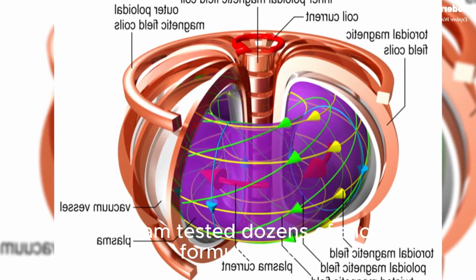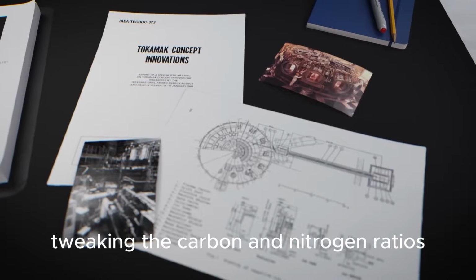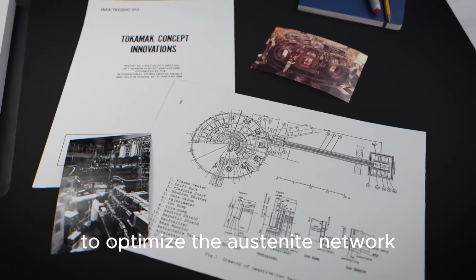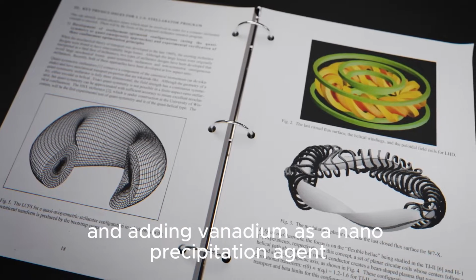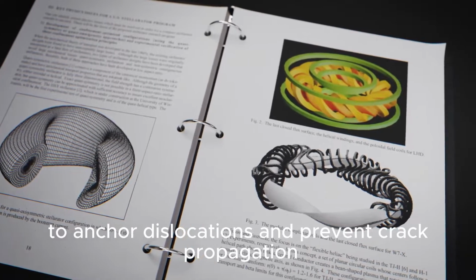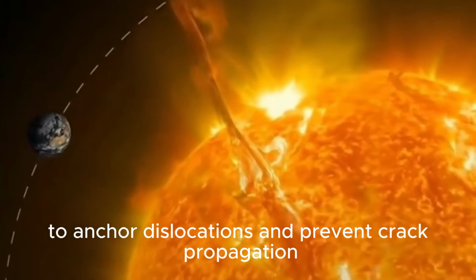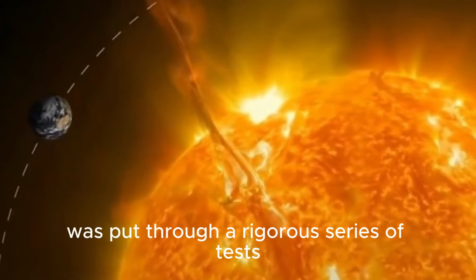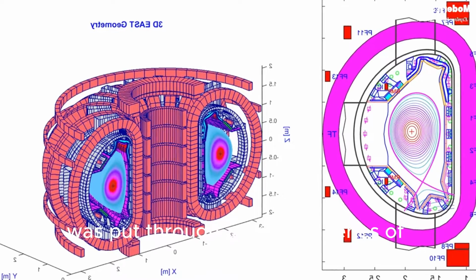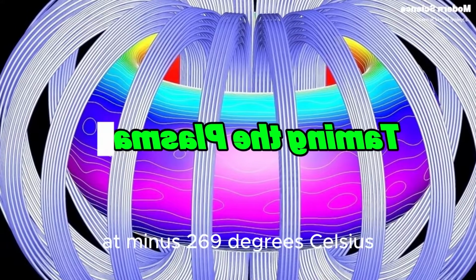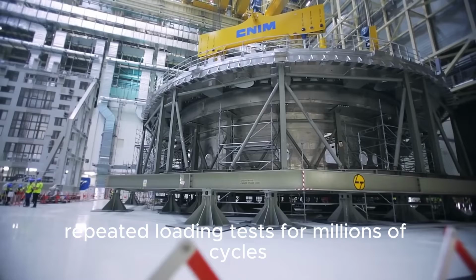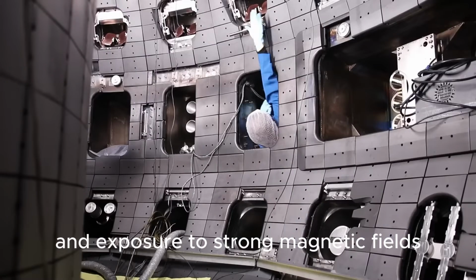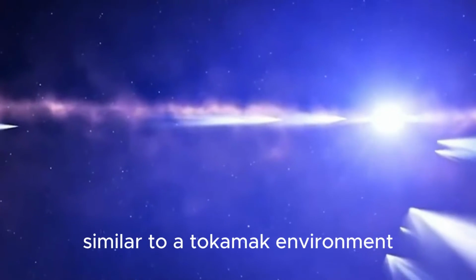From 2013 to 2016, the team tested dozens of alloy formulations, tweaking the carbon and nitrogen ratios to optimize the austenite network, and adding vanadium as a nanoprecipitation agent to anchor dislocations and prevent crack propagation. Each time, the steel sample was put through a rigorous series of tests: compression and tensile tests at -269°C, repeated loading tests for millions of cycles, and exposure to strong magnetic fields similar to a tokamak environment.